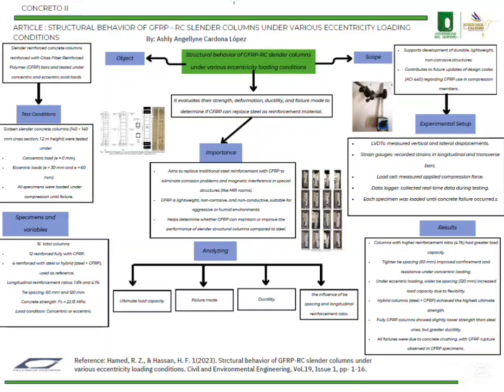Now let's talk about the methodology and testing program. The researchers prepared 16 reinforced concrete columns, each with a square cross section of 140 by 140 millimeters and a height of 1.2 meters. These columns were divided into several groups to analyze four main variables: type of reinforcement, longitudinal reinforcement ratio, tie spacing, and eccentricity of the load. They tested three levels. During the test, they measured deformation, displacement, and applied forces using several instruments: LVDTs for displacements, strain gauges to record bar strains, load cells to measure the applied load, and a data logger to continuously record all measurements.